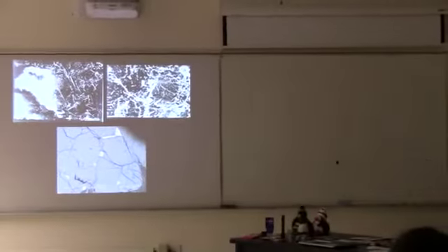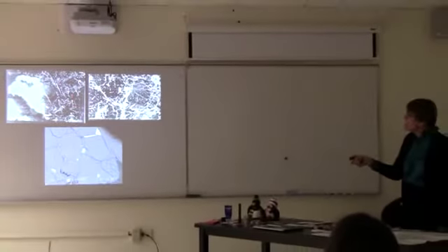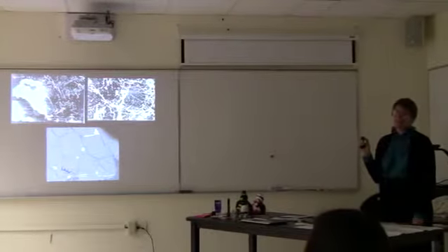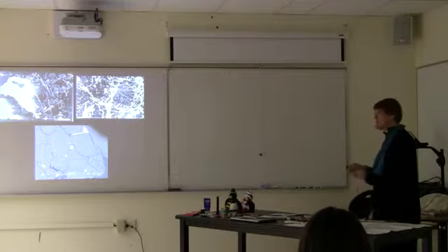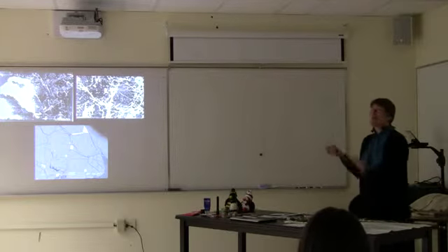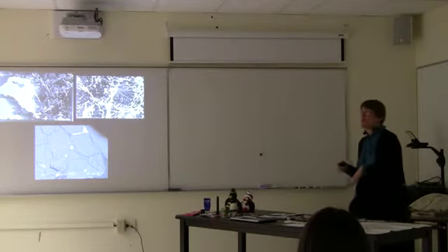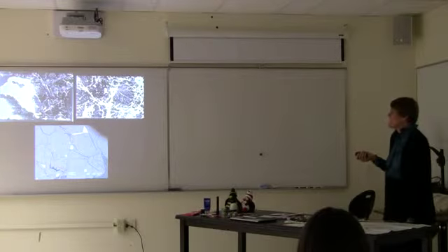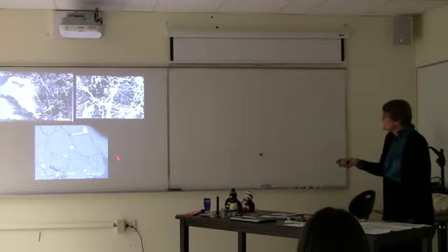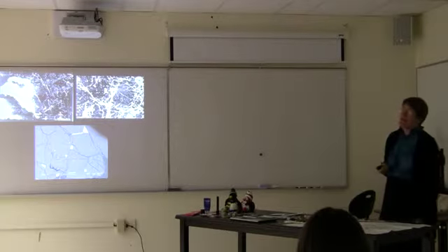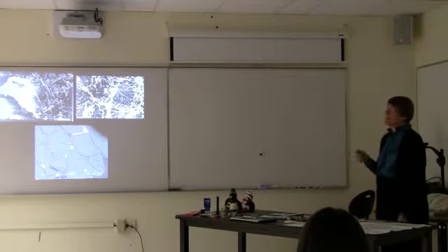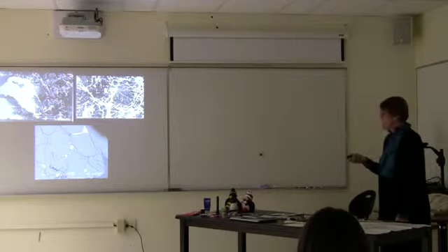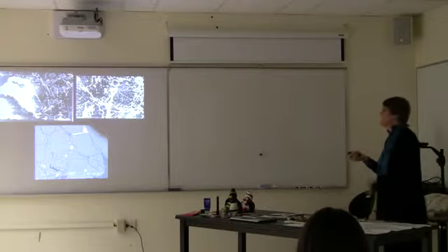So I went back and looked, and this is what those early images I was working with looked like. I'm going, oh, no wonder my values are so bad. Those are absolutely atrocious SEM images. I didn't acquire them. They were provided for me in the early days, because I don't have an SEM at Alma College. This is what we're acquiring now when I do my imagery. So I can see why I got absolutely atrocious numbers, so I tended to discard those from my data set and have gone back and re-imaged some of these with the way I do it.